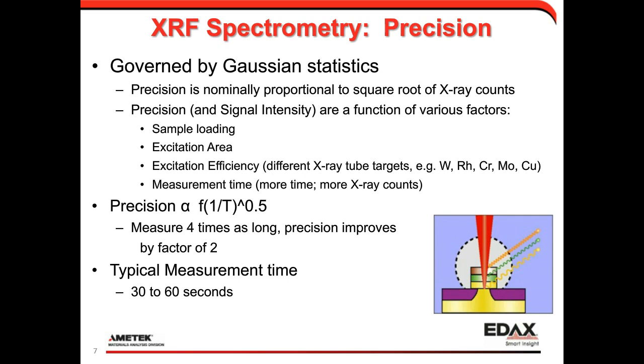The more measurement time that you have, the more X-ray counts you get and the better precision you have. So if you increase the measurement time by a factor of 4, the precision will improve by a factor of 2. General measurement times that we use in XRF, depending on what kind of precision you need, typically run anywhere from a few seconds all the way up to a minute. We can set the systems up, of course, to measure for longer as well if we're trying to measure something particularly difficult to get good precision on, some sort of trace or very thin coating, for example.